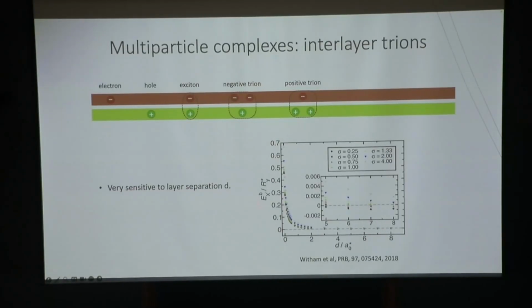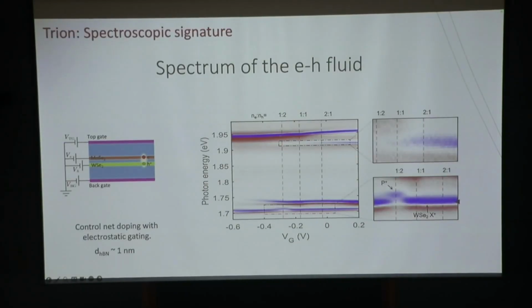So the theory predicts you need to control things within only a few nanometers. So we push the limit to see the strongest effect. We only use 2 or 3 layers of hBN in this case. In that case, we can again look at the spectrum as a function of our gate voltage. In the middle vertical line, this is where the electron and hole density remains 1 to 1. So this is the exciton regime.